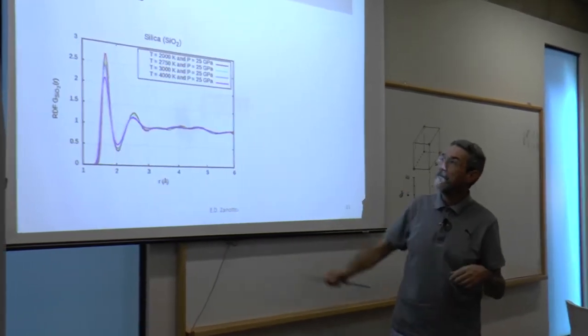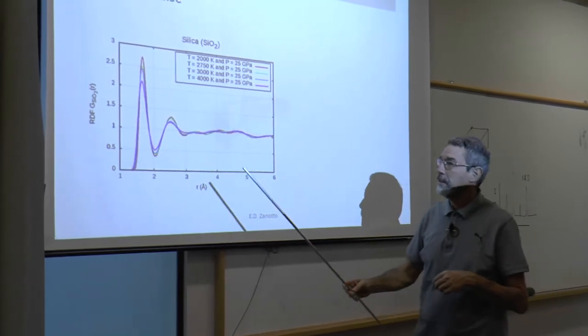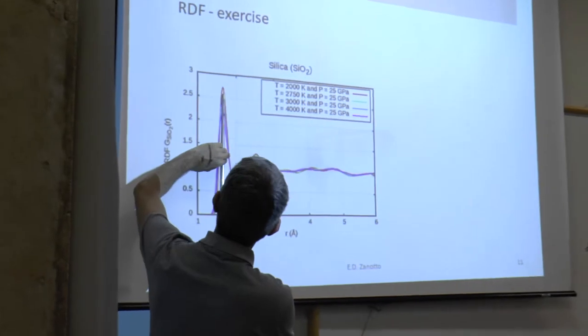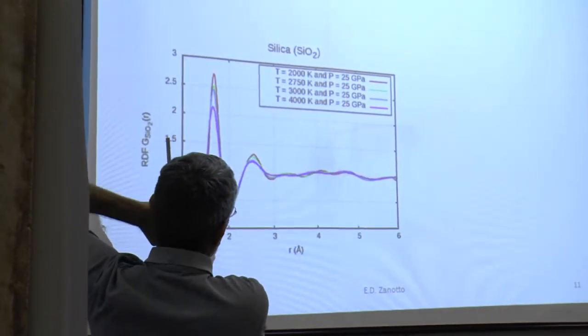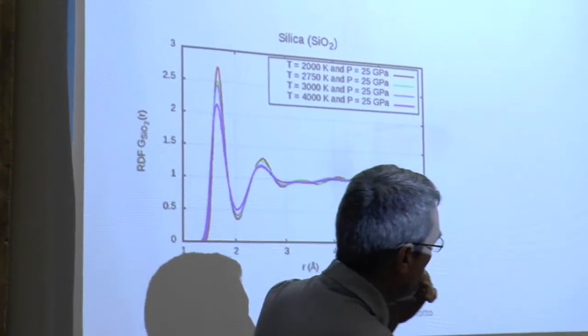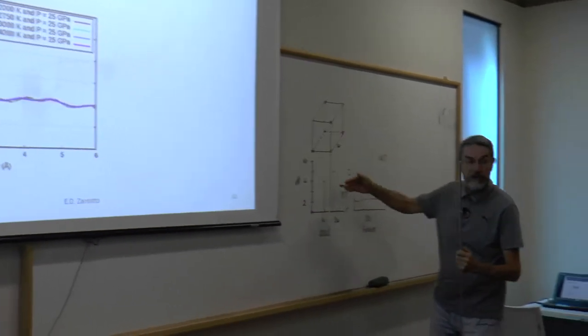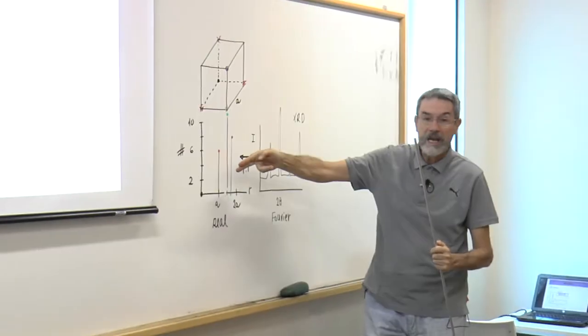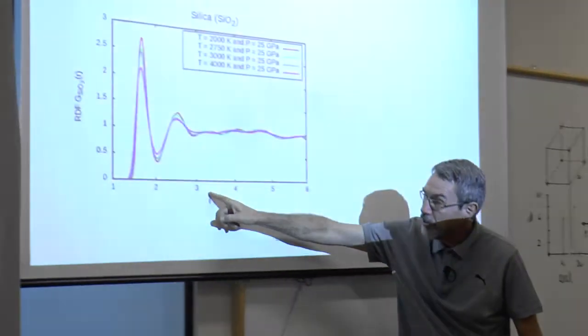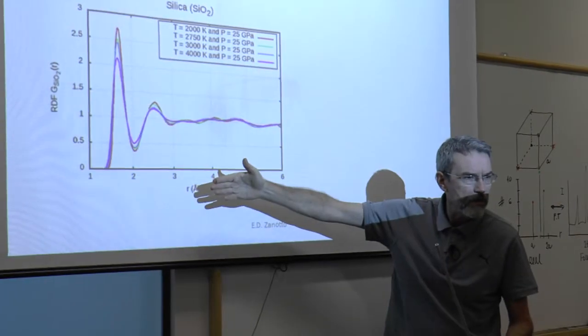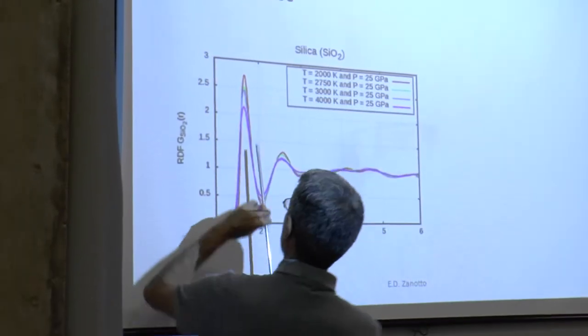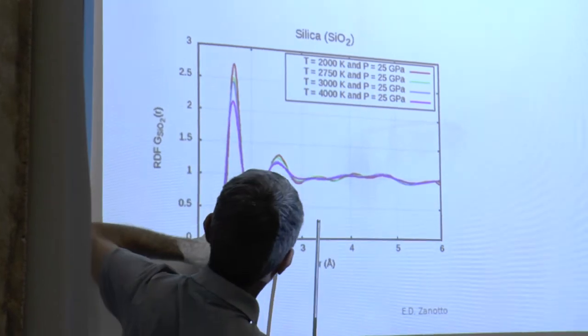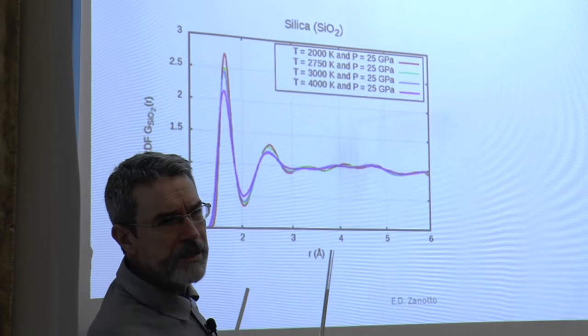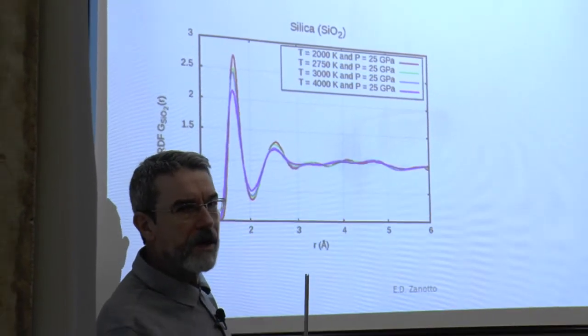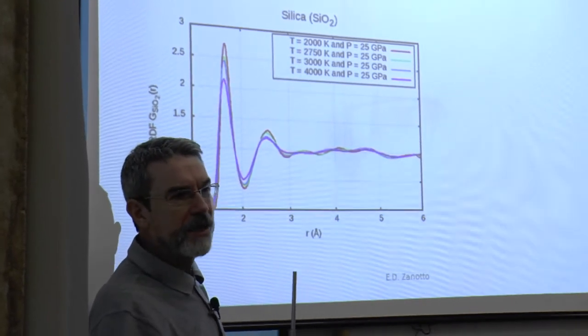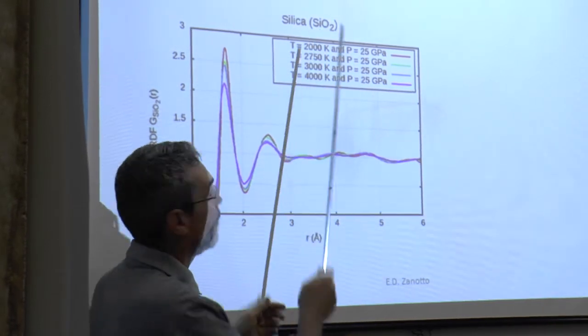For instance, in the silica glass, we have the silicon-oxygen distances. The silicon-oxygen distance comes from here, 1.5 angstrom. This is in angstrom. This is already the Fourier transform of the X-ray diffraction. The Fourier transform of the X-ray diffraction gives information in the real space, and it's angstroms here, so it is already the real space of the glass. So 1.5 angstrom, more or less, is the silicon-oxygen distance, which is exactly the same as the silicon-oxygen distance in the crystalline form of silica.